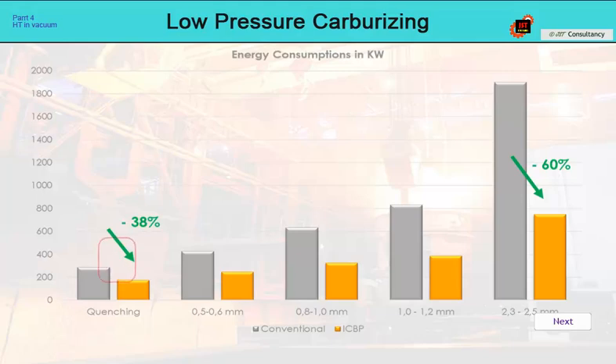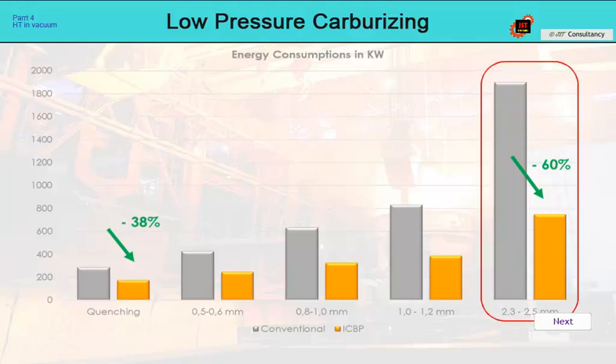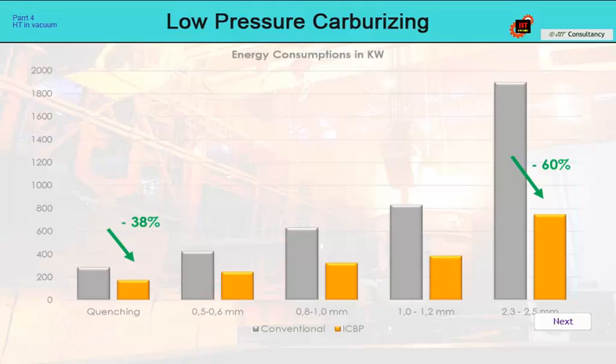This figure shows the electricity consumption for the quenching process in the LPC furnace and for the different carburizing depths for the reference load. The economic advantage increases with the required CHD, and we can achieve up to 60% savings. This, of course, will be reflected not only in the economy but also in emissions and lower carbon taxes. The reason is the possibility to work not only with better insulation properties of vacuum furnaces, but also with higher temperatures and higher diffusion rates.